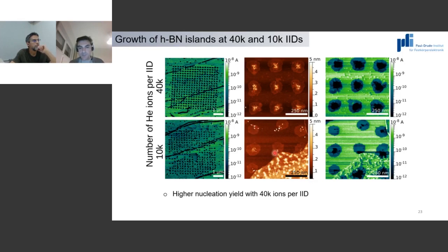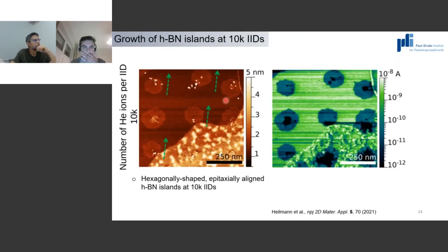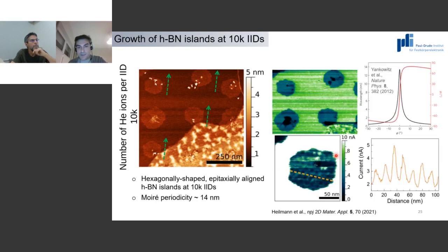And what is nice to see is that if you look in detail, you see that most of the islands are epitaxially aligned, but the arrows here are indicating the direction of the facets that you have on these monolayer HBN islands. And what is nice is that now if you look at the islands here by using conductive AFM, you actually see some moire patterns in most of the islands. I mean, remember, this was done with normal AFM in atmosphere, so it's not a fancy AFM in UHV and so on, but still we were able to see this moire pattern.